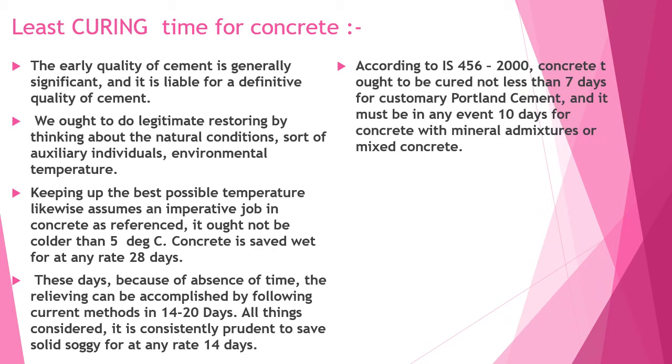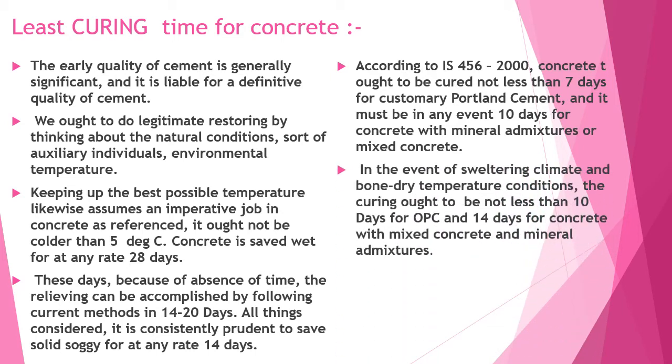According to IS 456, concrete should be cured not less than 7 days for ordinary Portland cement, and it must be at least 10 days for concrete with mineral admixture or a blended concrete. In the event of hot weather and dry temperature conditions, the curing should be not less than 10 days for OPC and 14 days for concrete with mineral admixture.